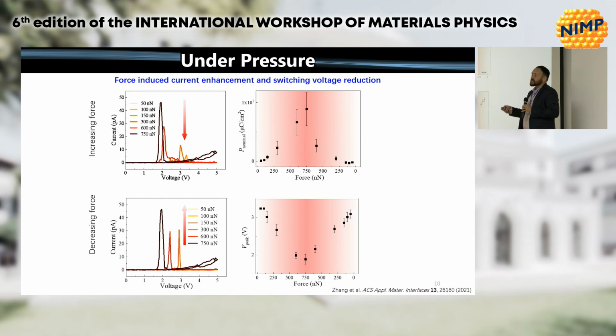And under the assumption that we have a 25 nanometer tip radius, and that's our contact, we can do a calculation of the polarization from these currents that we're measuring. And you can see that, while not perfectly symmetric, it is increasing with force and then decreasing with force again. And similarly, the switching voltage is decreasing and then increasing. And I think, perhaps surprisingly, it is changing the coercive voltage by a volt, which is quite large.